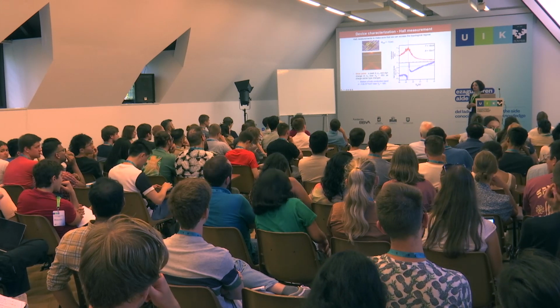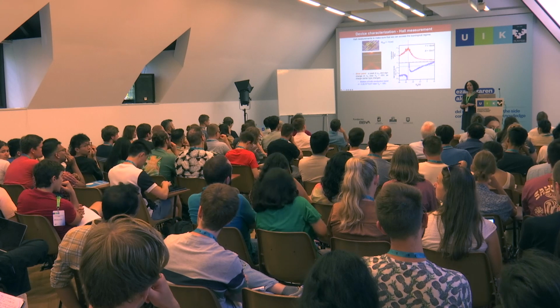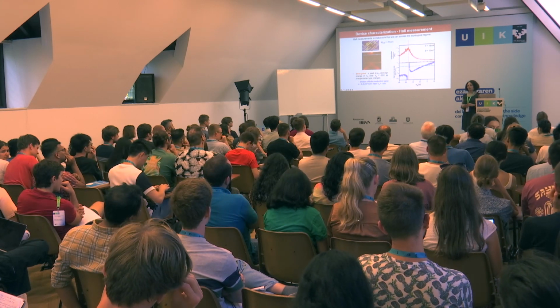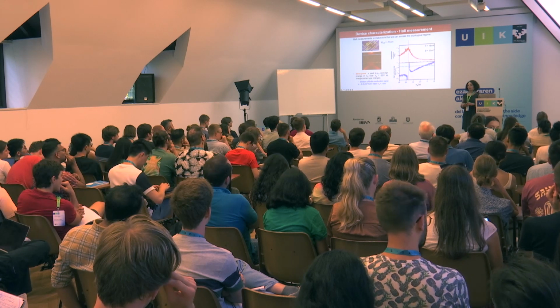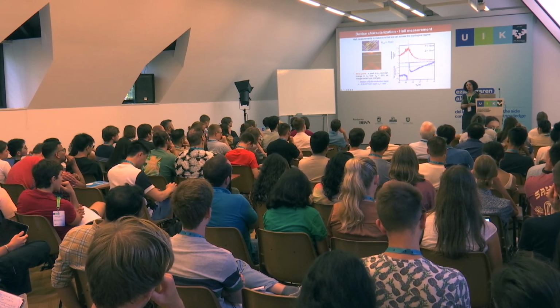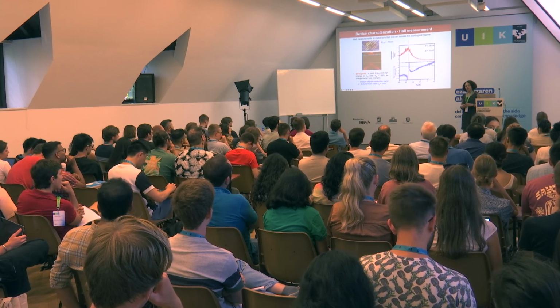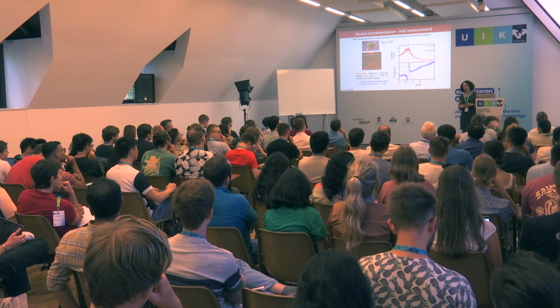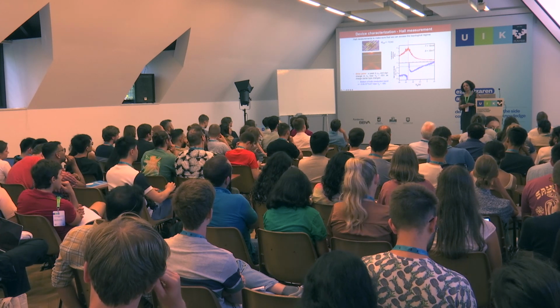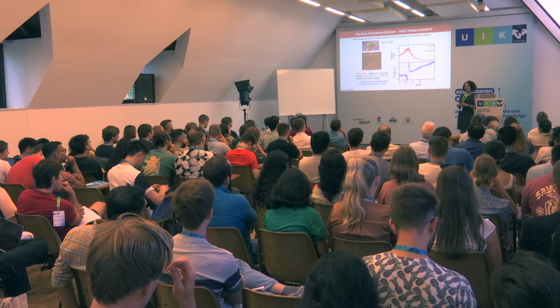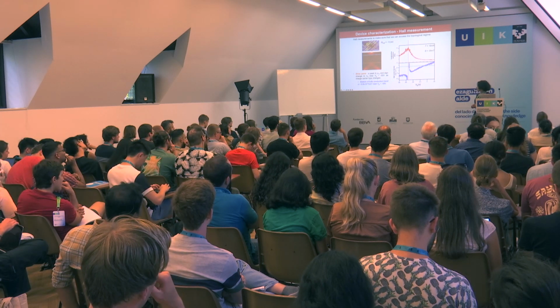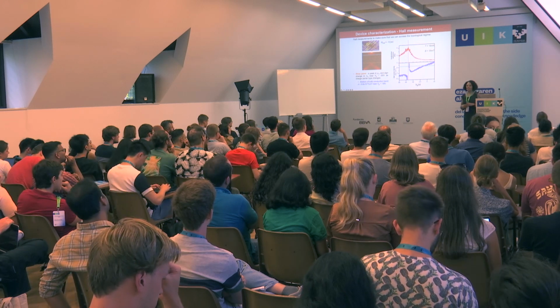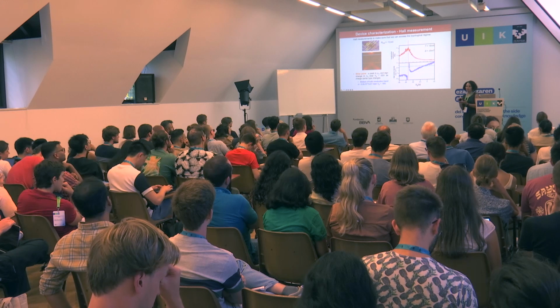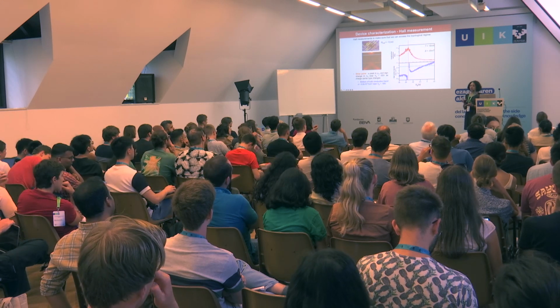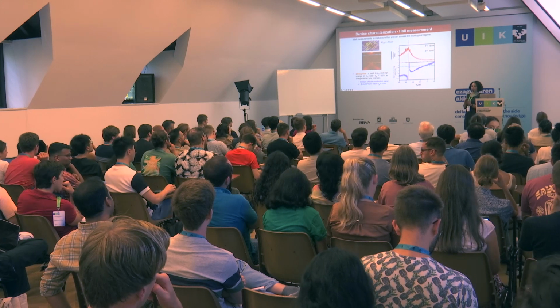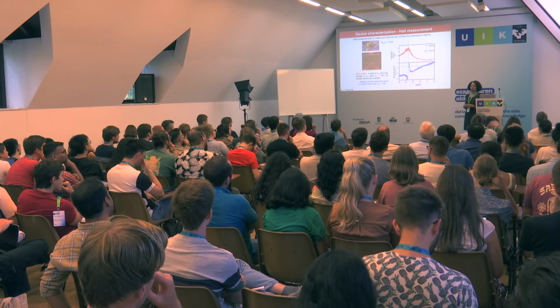Does that only work if you have a strong topological insulator? Sometimes it depends on the termination, right? Give me an example of what material you think it wouldn't work on in this case. A weak topological insulator, or something that depends on the substrate? So in this case, we assume that we have surface states on the top and the bottom. Is that your question? I'll show you that we think we do have surface states on both the top and the bottom in this case. That's right, so it's a thin enough system that we ignore the sides.